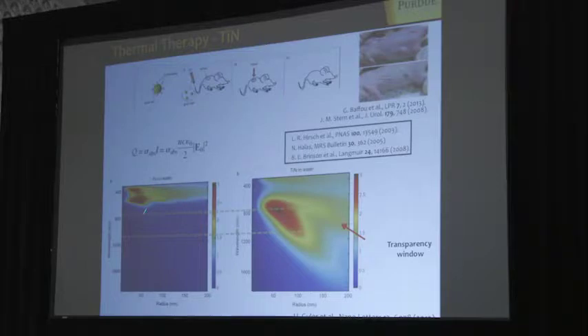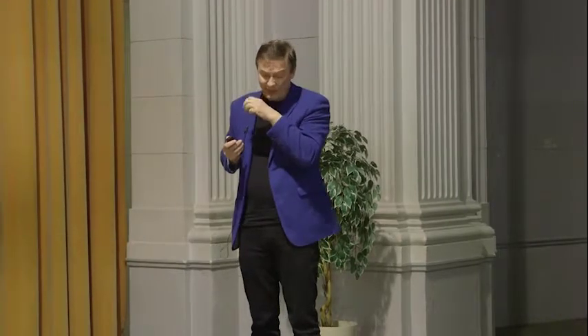The problem, though, is that for gold colloidal particles, this plasmon resonance is outside of the biological transparency window. It's like 540 nanometers. So therefore, they have to make these nanoshells. It's a dielectric core coated with gold. As a result, yes, the resonance shifts into this biological transparency window, but your particle becomes large. It also uses gold, and there are also some surfactants. Then the problem becomes how to remove these particles from your body, because they tend to accumulate in the liver and kidney.